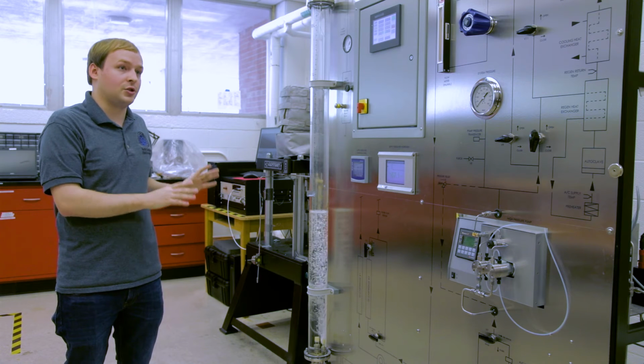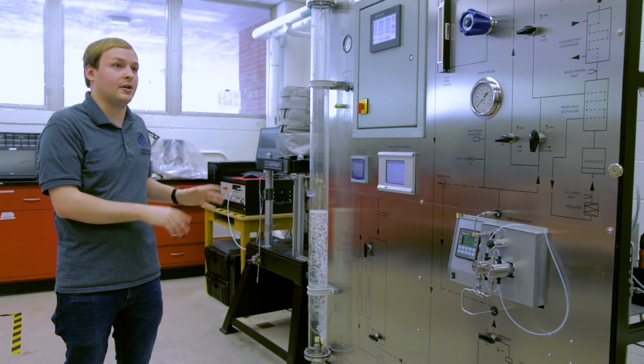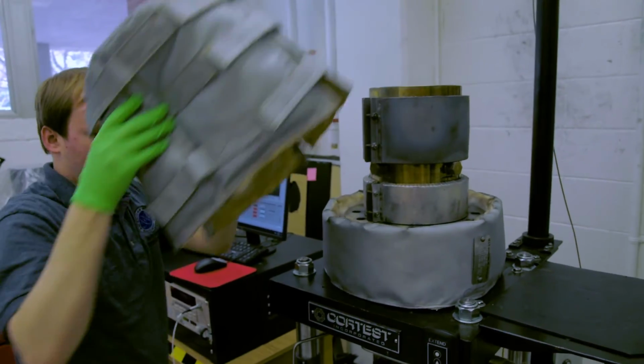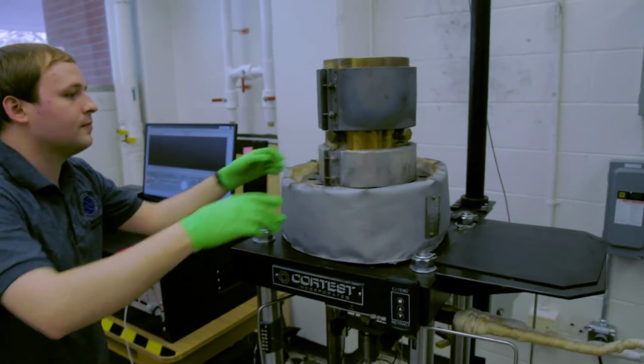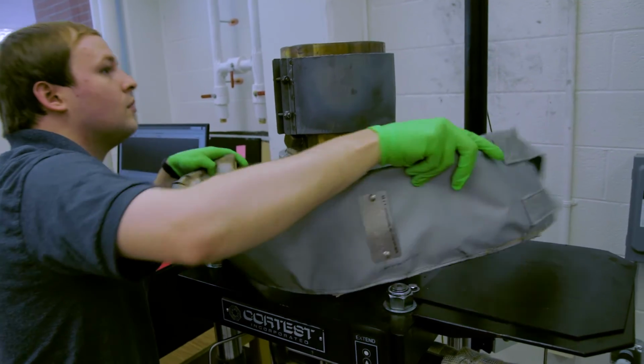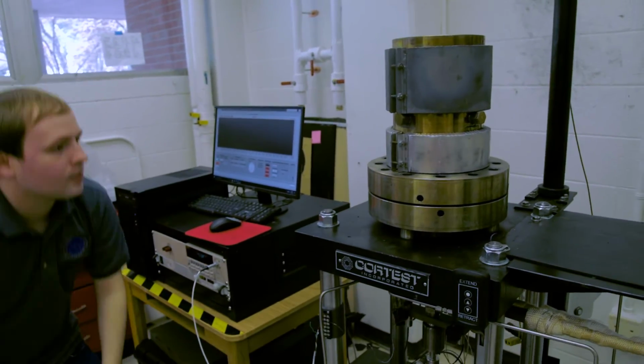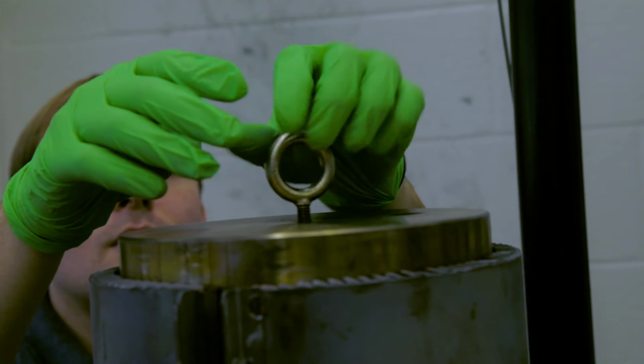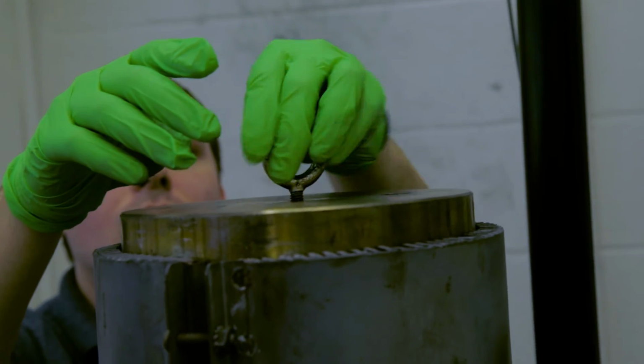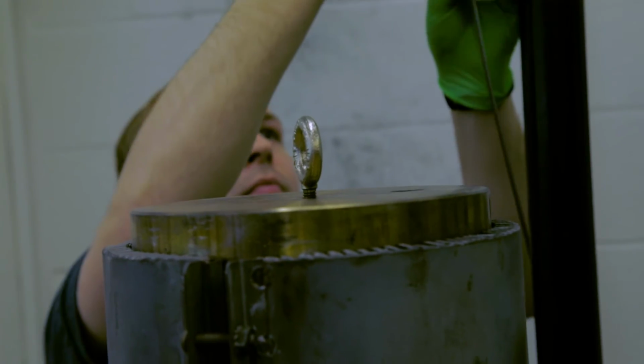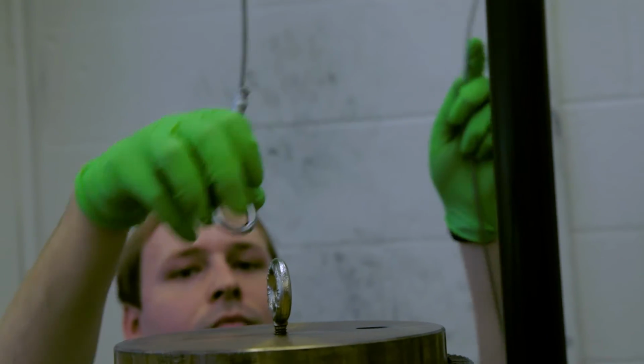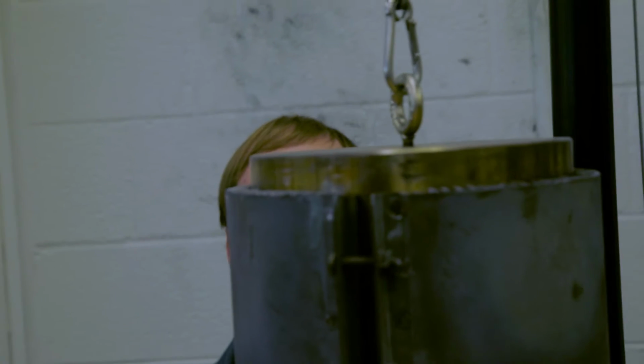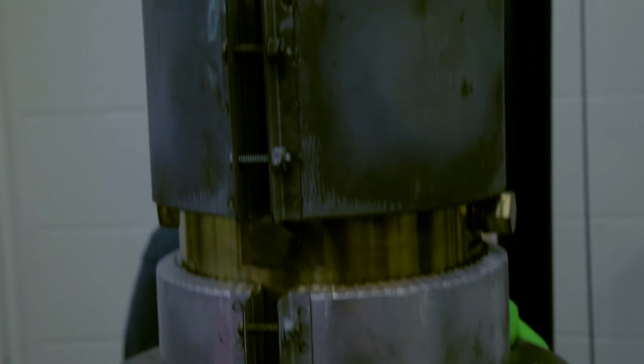The other interesting feature of our loop autoclave is that it also has a tensile machine attached to it, which allows us to add stress to our samples while we're running our tests, and that would be known as a stress corrosion cracking experiment. With that, we have a direct current potential drop system, which allows us to measure the potential drop over the course of time and relate that to the crack length so that we can get something like the crack growth rate, which is an important parameter.